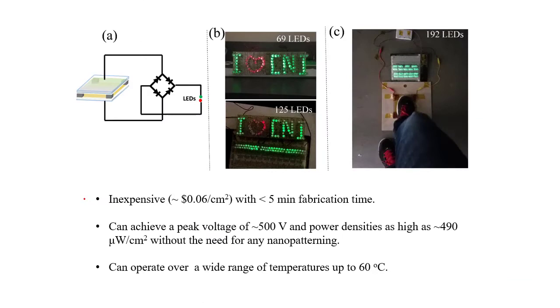For example, here, you see my student. He developed a triboelectric nanogenerator that was able to power up things like 200 LEDs. So here is an example video. So this is a triboelectric nanogenerator. What you see here, that is the same thing as what I have shown you. Just a PET layer coated with ITO and some Kapton tape. That's it.